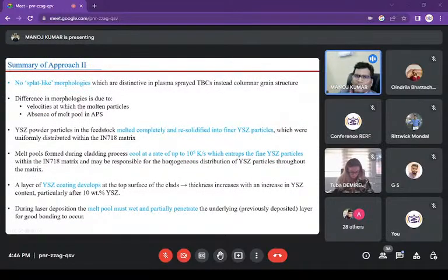Now summarizing approach 2, we find that it is a very different macrostructure compared to typical deposition of thermal barrier coating by plasma spray. In the plasma spray, we get a splat-like morphology. Here we get a dendritic structure, which is advantageous for retaining the strength at elevated temperature. And this is possible because the velocity is very different.